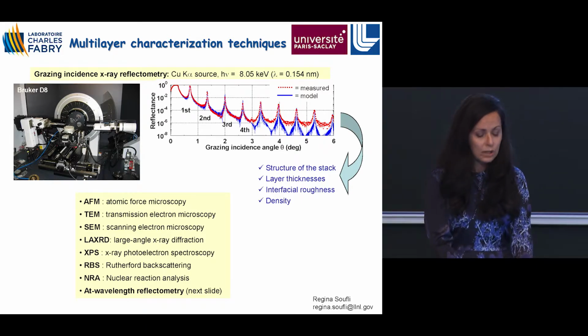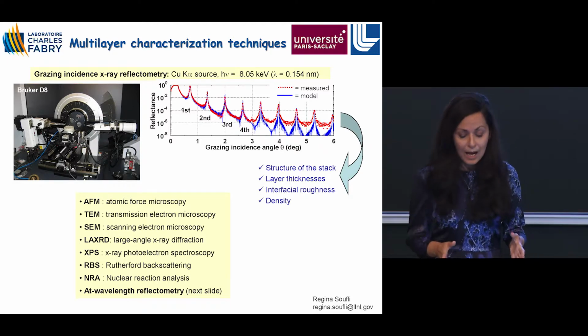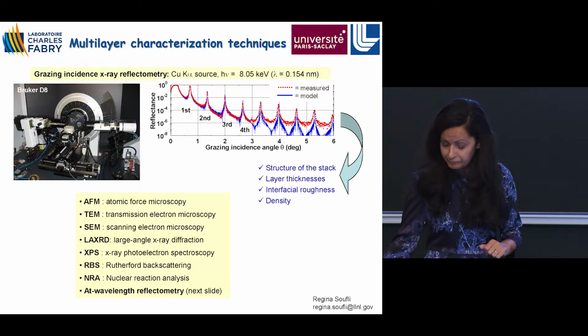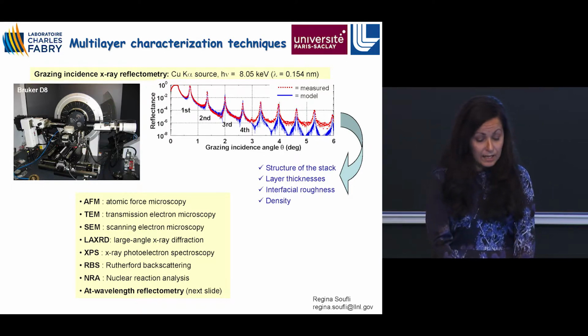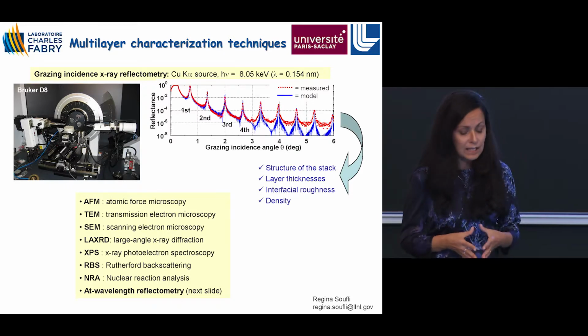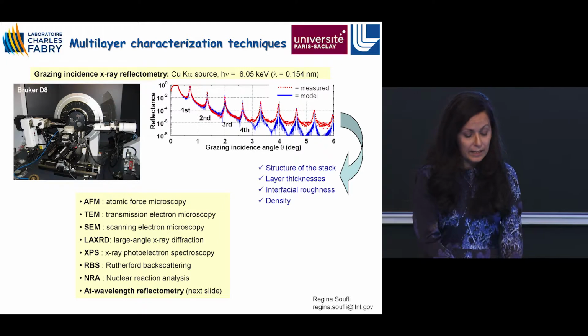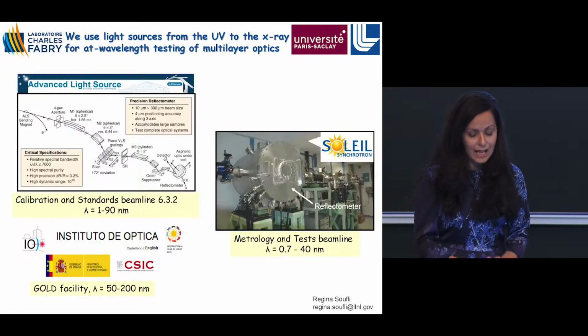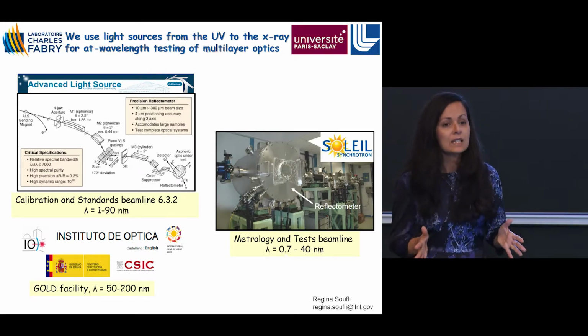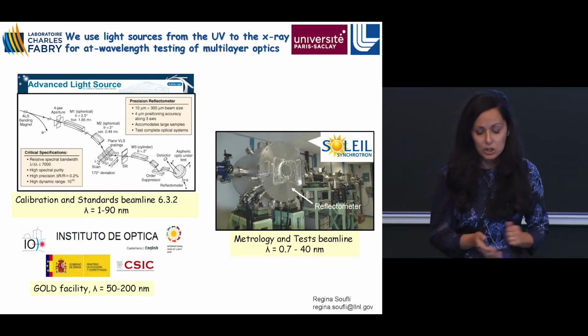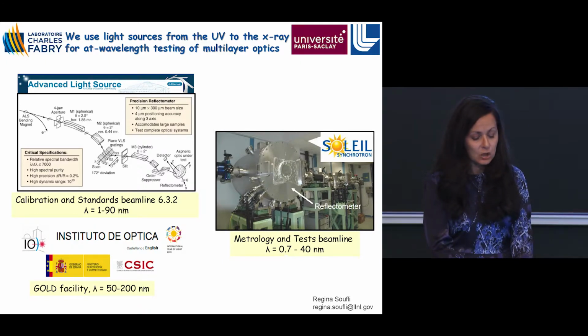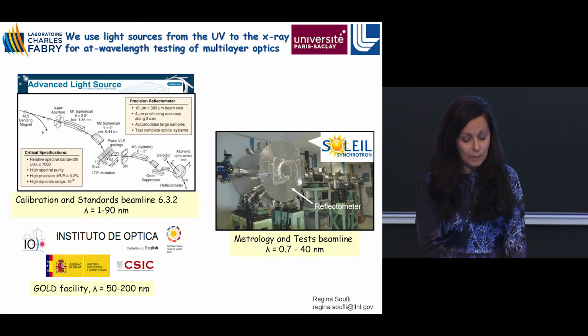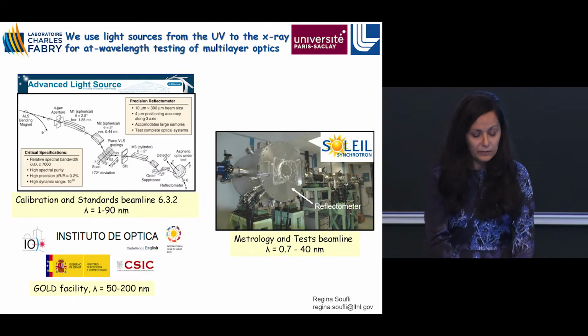We also have here a suite of other characterizations. AFM, TEM, and SEM can provide highly localized information about morphology and crystallinity. XPS, RBS, and NRA can give information about density, atomic and chemical composition. And finally, one of the most important characterizations is at-wavelength reflectometry. The ultimate test is to measure your coating at the photon energy where it is going to operate. So for this presentation, we have used beamline 6.3.2 at the Advanced Light Source Synchrotron, Lawrence Berkeley Lab, the metrology and test beamline at the Soleil Synchrotron, and our collaborators' facility in Spain, the GOLD facility.